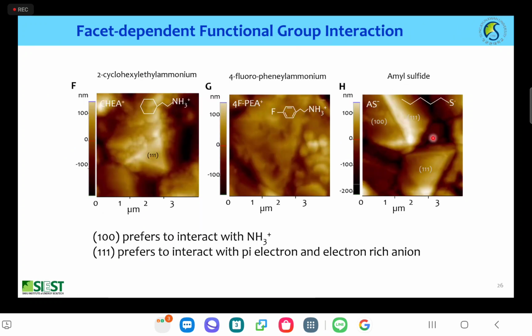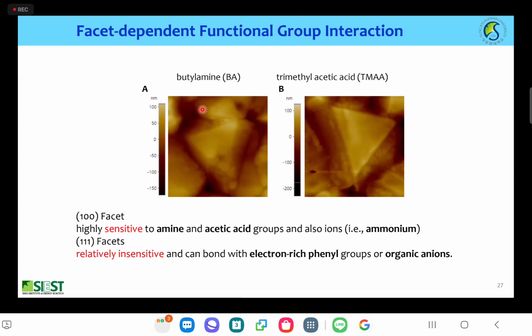So we investigated various kinds of materials, including cyclohexyl and pi electron groups, and also anions and neutral molecules. Finally, we concluded that the 100 crystal facet is highly sensitive to amine and acetic acid groups, and also to cations such as the ammonium cation. The 111 crystal facet is relatively insensitive, however, it can bond with electron-rich phenyl groups or organic anions.